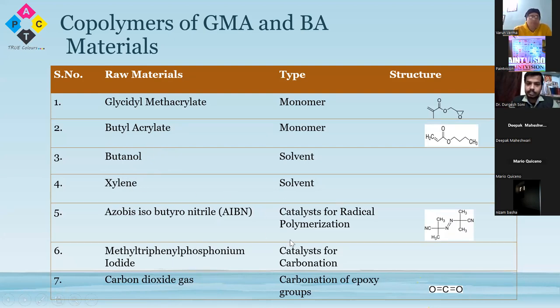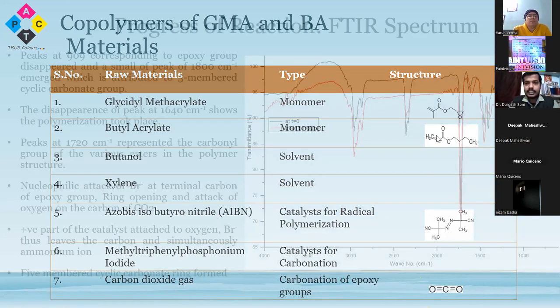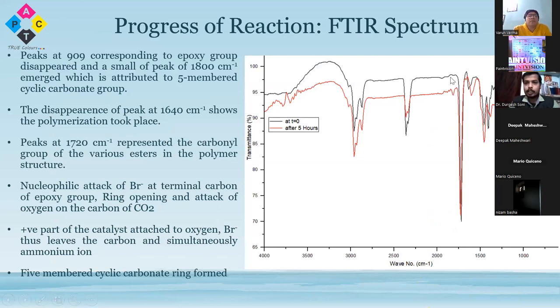And the catalyst was the same, AIBN, for the free radical polymerization. And for the carbonation, a second catalyst was used, which is methyl triphenyl phosphonium iodide. So again, in this reaction, we can see that a small peak is generated corresponding to 1800, which was initially absent. In the black, we can see there is no peak at 1800. And in the red graph, the new peak at 1800 emerged, which was attributed to the cyclic carbonate group.